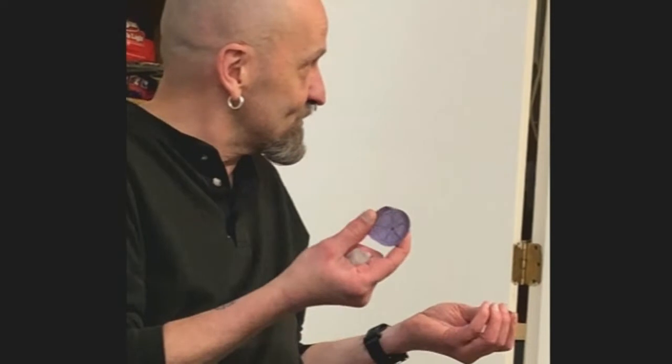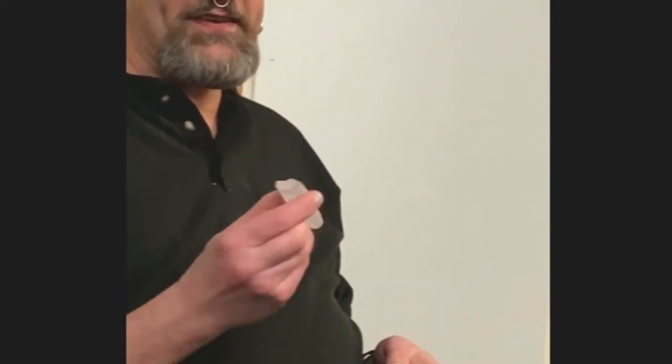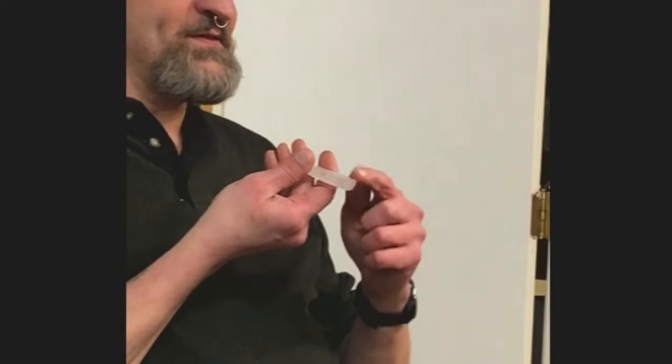If you ever see shapes like these, you're definitely in synthetic land. These are all called boules - sometimes completely round, but basically shaped like bullets, and they're grown crystals. Sapphire is often split to relieve the stress and then heated again - that's called annealing. If you see a shape like this cross-section of an unsplit boule, you know you're dealing with synthetics.